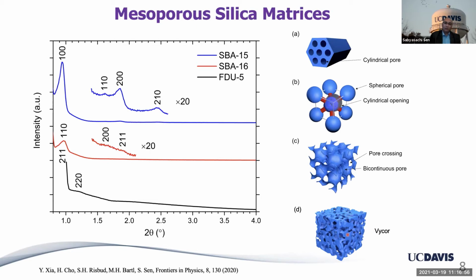And then I'll also talk about Vycor as a confining medium, except these are not commercial Vycors. Vycors are phase-separated glasses where you leach out one of the phases to create these continuous but tortuous pores, nanopores. But in our case, these are further treated. The commercial Vycors have 5 to 8 nanometer pores, but these have 11 to 15 nanometer pores because we treated them further with acid and so on. So that's the confining medium that we'll be using.